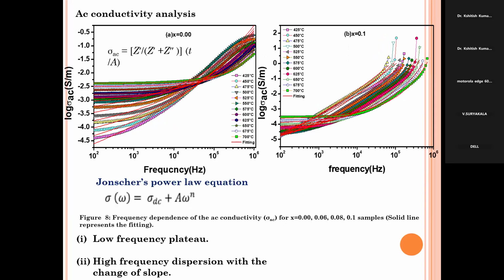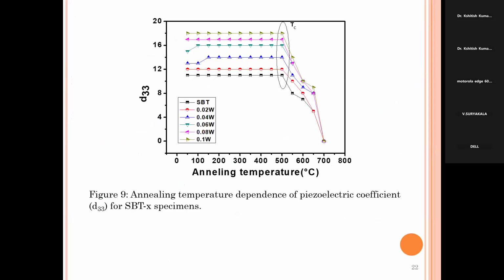And after that, we have taken the AC conductivity. As I told, in the doped material the resistance is more, so the conductivity is less. So here we have taken the conductivity. There are different equations, and we have fitted the equations with Jonscher's power law, and from that we can calculate the DC conductivity and how it is related to temperature. And after that, we have found the grain resistance, the grain boundary resistance, the AC conductivity of the material, the DC conductivity of the material, and how they are related to frequency and temperature.